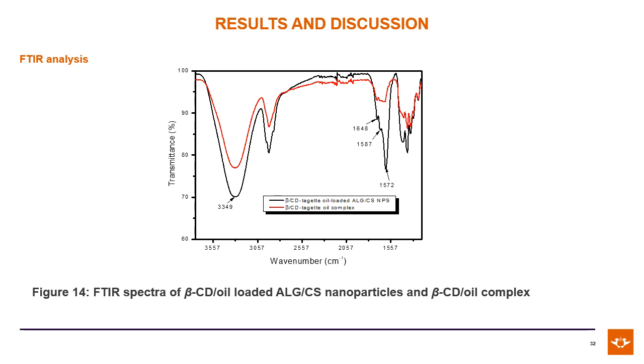The FTIR spectrum of beta-cyclodextrin and the inclusion complex also confirmed the successful synthesis of our inclusion complex as well as the nanoparticles. In the spectrum of nanoparticles, the broad band at 3349 was attributed to a stretching vibration of OH. The bending vibration of NH at 1587 and the asymmetric stretching of the carbonyl group at 1572 were characteristic of the presence of chitosan and alginate, respectively.